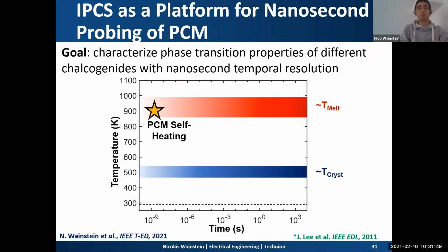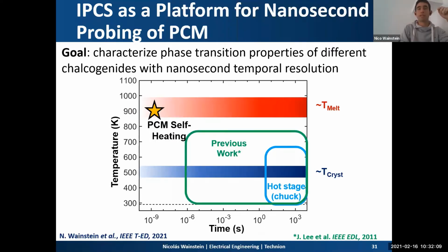The classic way to probe temperature-dependent characteristics is usually the hot stage. The hot stage can provide middle-low temperatures and timescales that are several seconds to minutes. So it's not possible to be on this side. Previous works, such as the microthermal stage, achieved middle-high temperatures with microsecond temporal resolution, but still not down to the nanoseconds that are required for the self-heating, which is for the quench process, or the heating and quench process, that is the amorphization. So there's still a need for a platform that can properly probe the thermal actuation with nanosecond temporal resolution and heating capabilities up to the melting temperature.